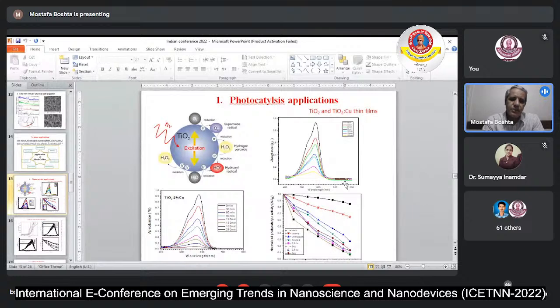So I use the titanium oxide with crystal violet dye, and we can see that with different times the catalyst can affect the dye and decrease the absorption of the material. And also with copper, when we add the copper to the titanium dioxide, it gives us more efficiency and more decaying of the dye in the solution.